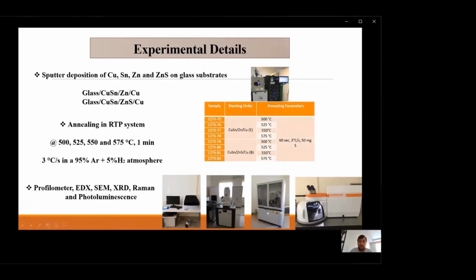As I said before, we use two stacking orders, E-type and B-type samples, and we use 4 different temperatures for each sample. So we numbered the samples as 75, 76, 77, 78 according to their sulfurization temperature for E-type, and CZTS 79, 80, 81, 82 for B-type samples according to their sulfurization temperatures.